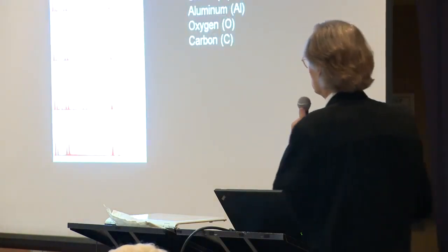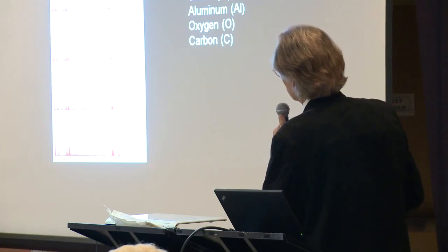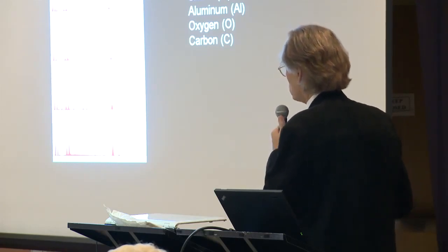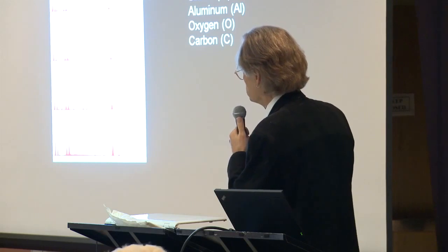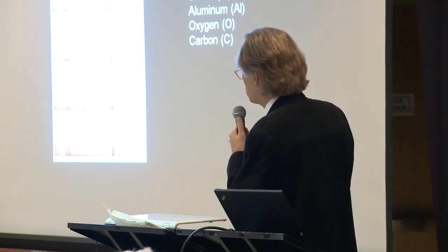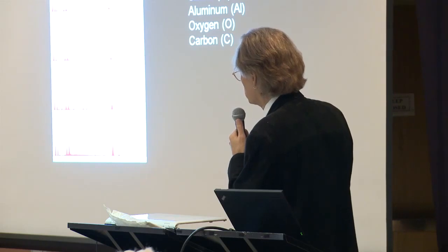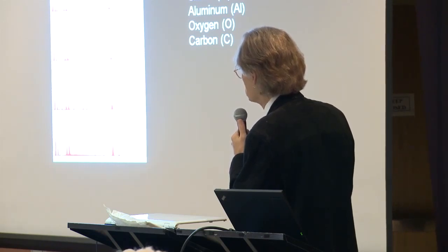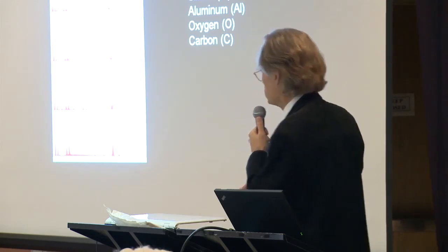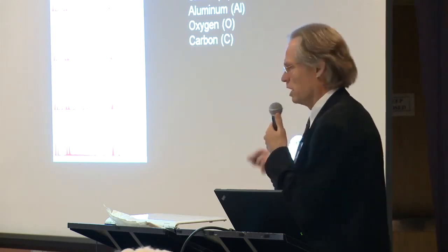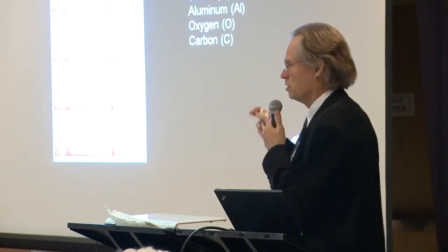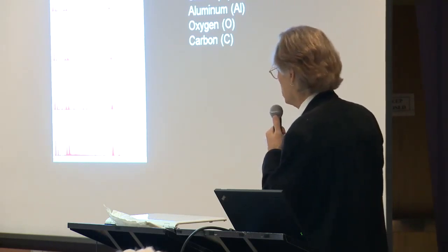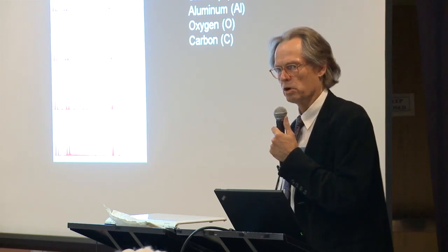And these so-called energy dispersive spectroscopy results from the 4 samples are already showing us. I'll pick the lowest one. They look small, but this is because the carbon peak is so big. Carbon is C, O for oxygen, Fe for iron, Al for aluminum, Si for silicon, and these are 2 other iron peaks. Look at the lower one. These are the elements, and there's nothing else in the red phase, the red layer. Iron, silicon, aluminum, oxygen, and carbon. Very simple composition, actually.